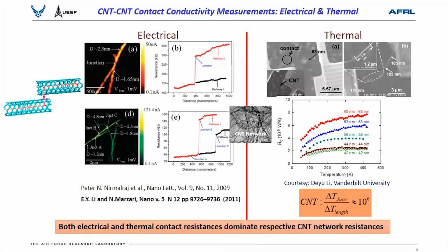So what is the bottleneck and what is the challenge? If we want to pursue this network carbon nanotube mesh, how do you design the interface? As I showed in the previous example, the interface is the key. Unless you do the right interface design, you will not achieve the properties. So there's a nice work over a decade ago. This is the work on dispersed carbon nanotube. Nothing is done on interface design, just laying one on top of the other. And with AFM, atomic force microscopy, they measured the electrical resistance of carbon nanotube along the length, then at the junction.